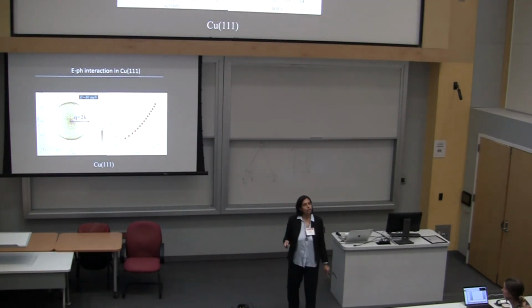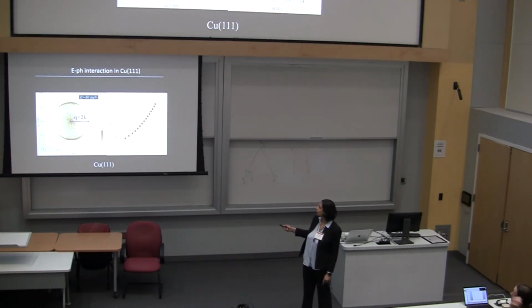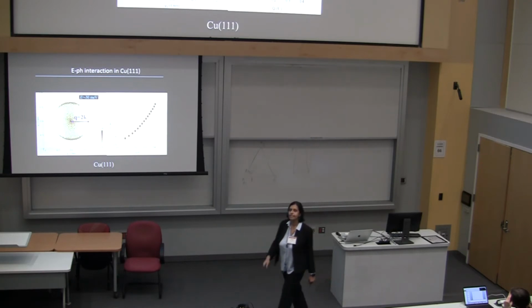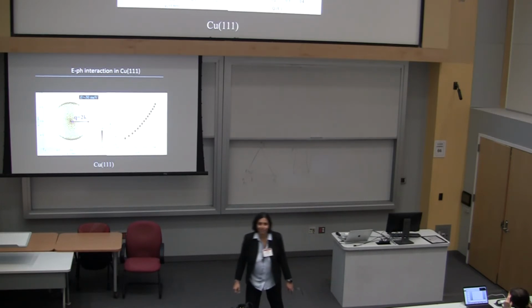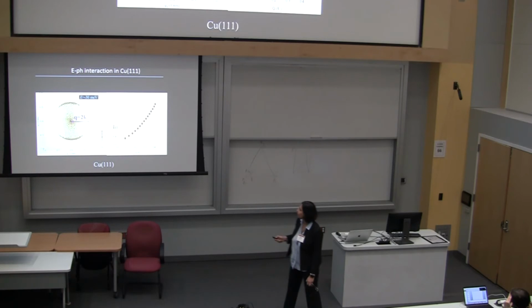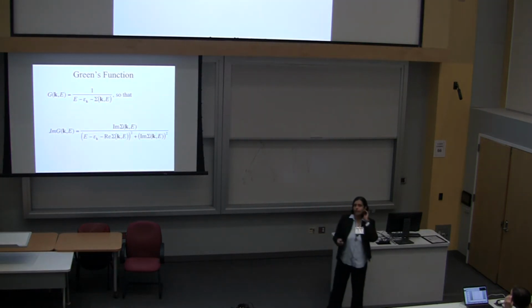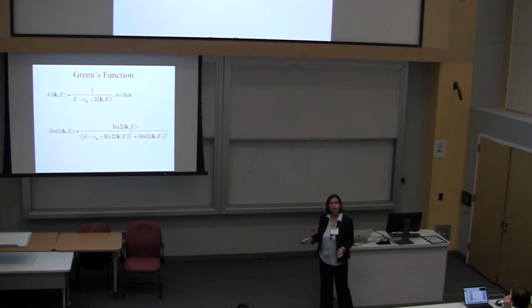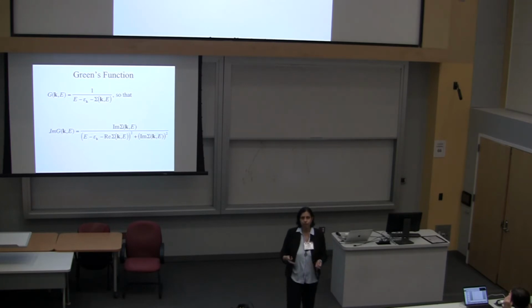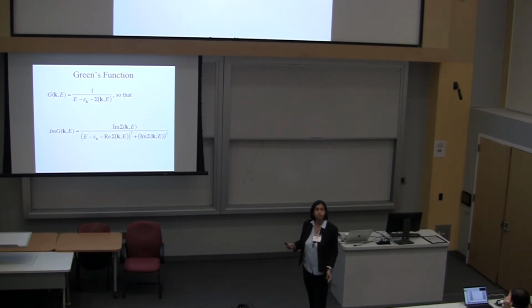So what did we really want to do? Here's the surface of copper. Here's the dispersion. Here's the Fermi energy, 0. We wanted to look very close here and see if we can see a kink in the dispersion. So that's what we were trying to do. So what do we do once we see a kink? First, let me just go back to some very basic thing, which is what are we measuring?